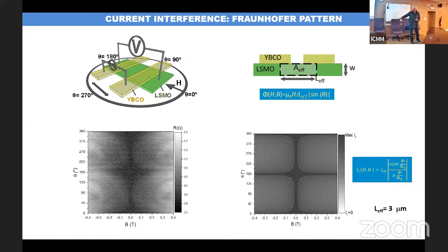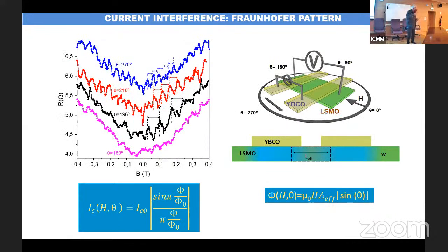This is differential resistance as a function of magnetic field for different angles. And basically, what this is showing, maybe you see it better in the simulation, the period of the oscillation is the shortest where the magnetic field is directed perpendicular to the junction, because there is flux across the junction. And when the magnetic field is along the wire, there is no flux threading the junction, and the periodicity goes to infinity. There is no periodicity. This is why we get these slopes. And this modulation of the period is what we got if we look at individual resistance curves.